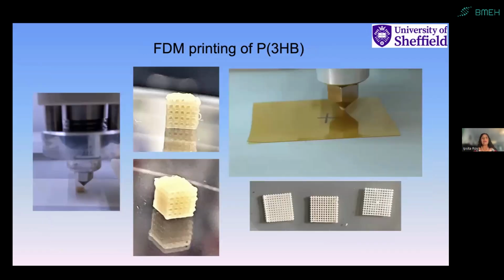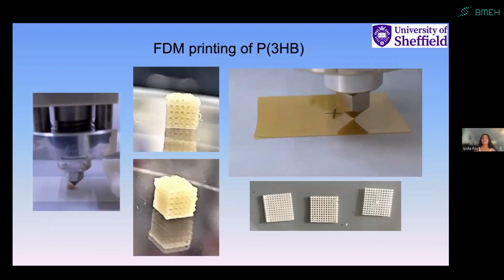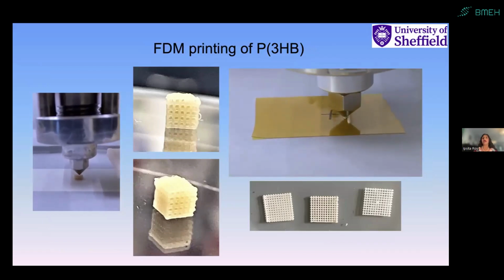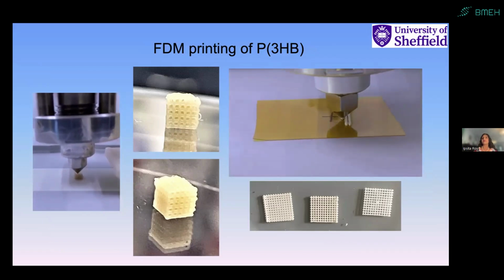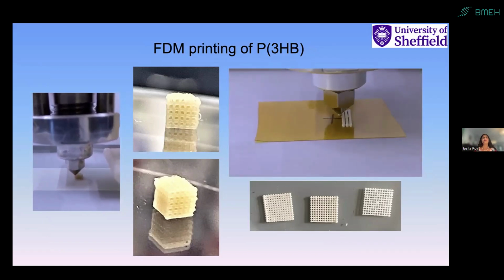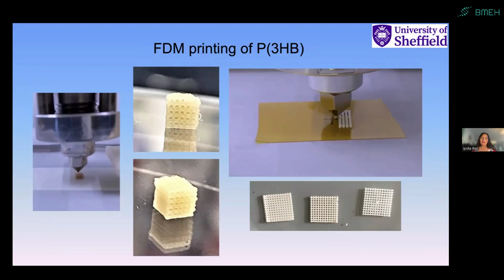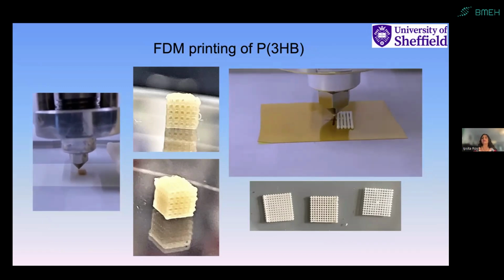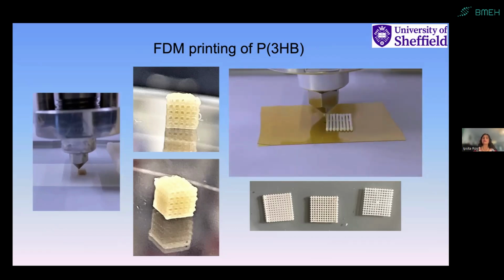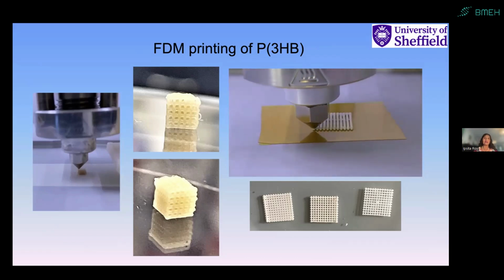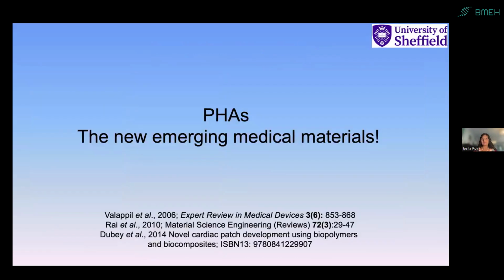This is P3HB. We have managed to print P3HB really well. There is always a kind of belief that P3HB cannot be printed very well because it degrades very close to its melting temperature. But we have used certain specific methods in order to print them successfully. The bottom ones are composites with titanium oxide that we created with P3HB.